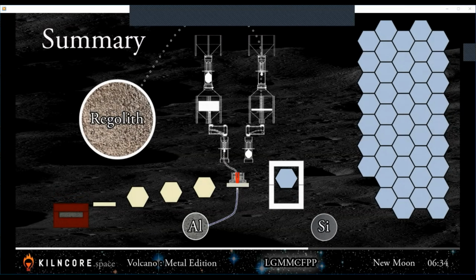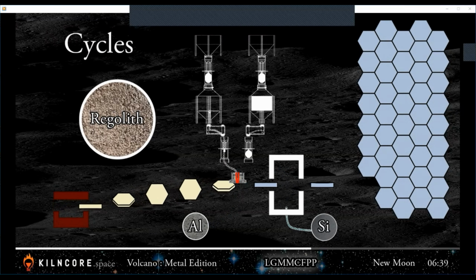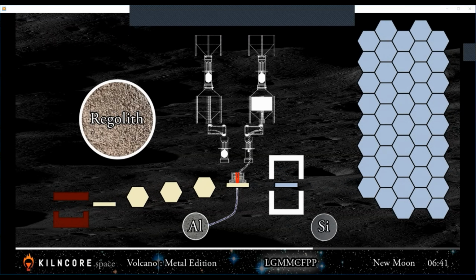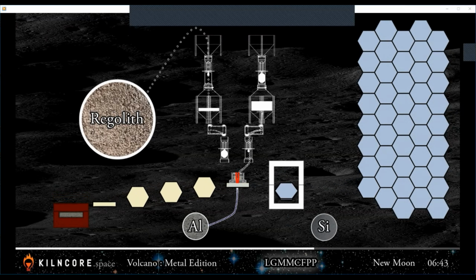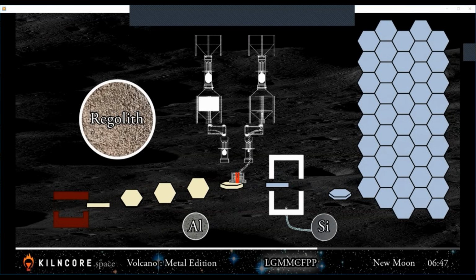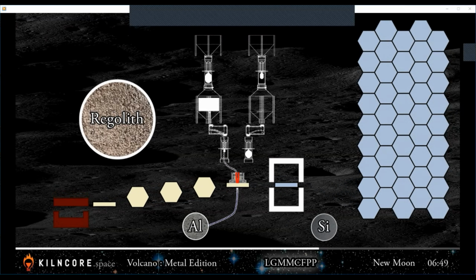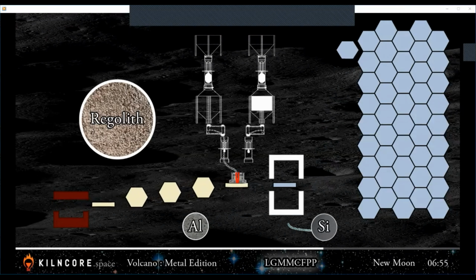The raw regolith is deposited in the currently depressurized reservoir. The reservoirs pressurize and depressurize in cycles. Regolith in the pressurized reservoir is fed to the reaction chamber, where high-temperature molten regolith electrolysis is done. Using an appropriately high column and a lower temperature section, which will crystallize the silicon while leaving the aluminum liquid,